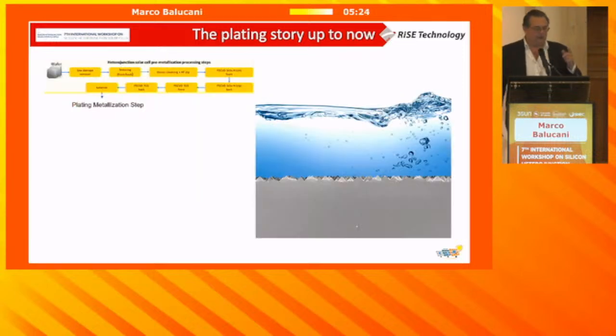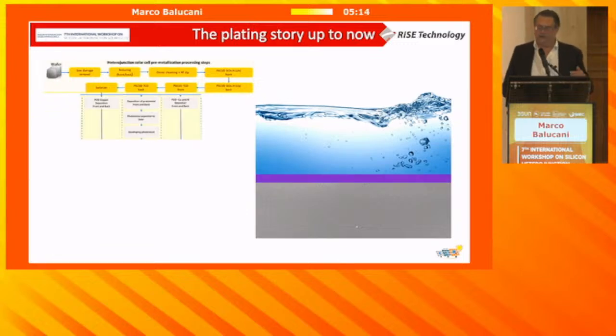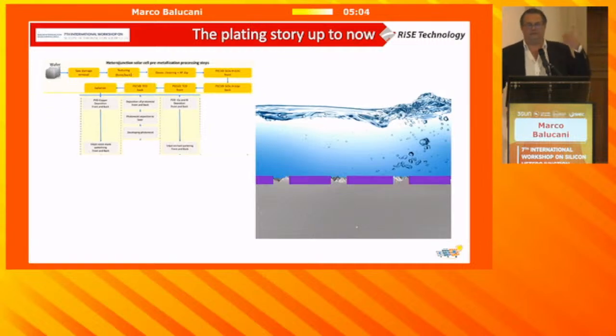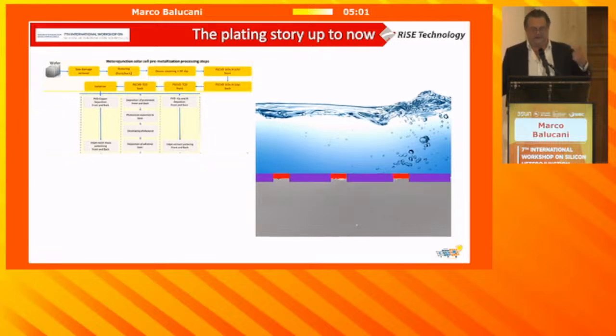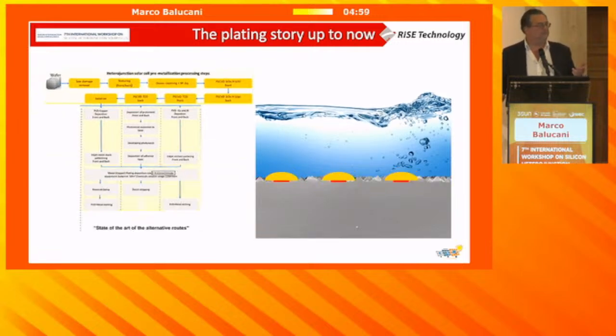So if we go through the plating, or the different techniques, in any case, the wafer is fully immersed in a solution, okay? The difference is in the step: you need to protect something. It can be a seed layer everywhere, like copper, we saw it before, or it can be a dielectric and so on. Then you have to do an opening, or before we were seeing lithography, seed layer, copper deposition, and then you can remove. So in any case, you are consuming a lot of solution, and you're wetting all the wafers, so you need a protective mask that will cost and that will cover.